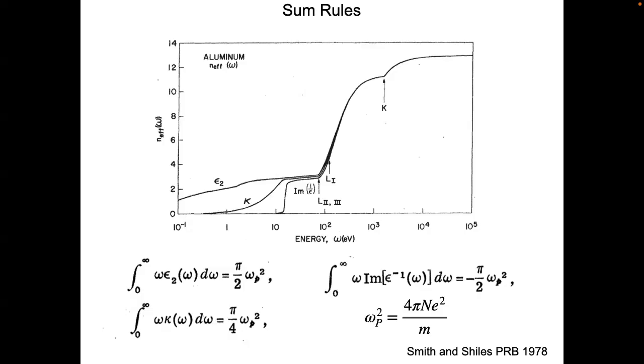If you talk to a chemist and ask them how many valence electrons aluminum has, you don't have to. You can just read it off from this plot here. It's 3. But if you keep going, it's not the valence electrons anymore. It's deeper core levels, and they exist at different energy scales. As you keep integrating, you hit about 100 eV, and these go by various names that X-ray people have given them: the L edge, the K edge, and on and on and on and up.